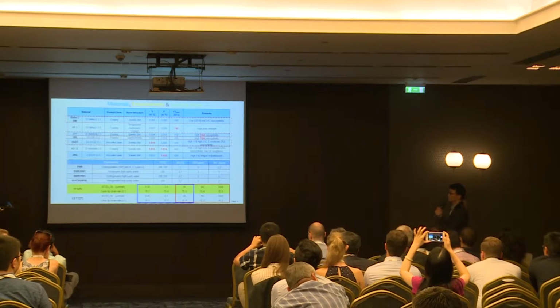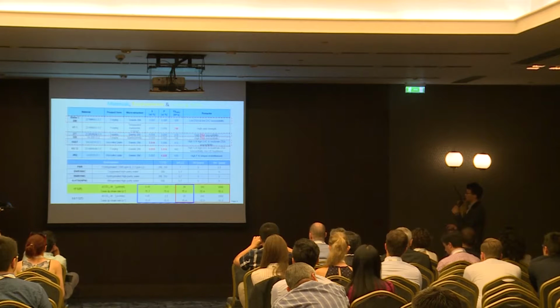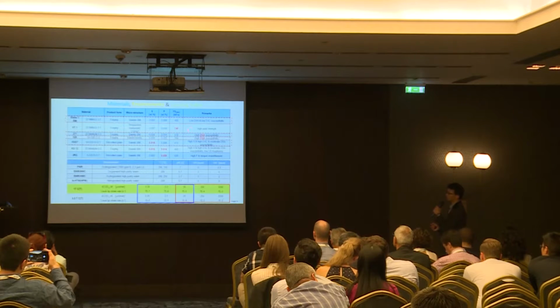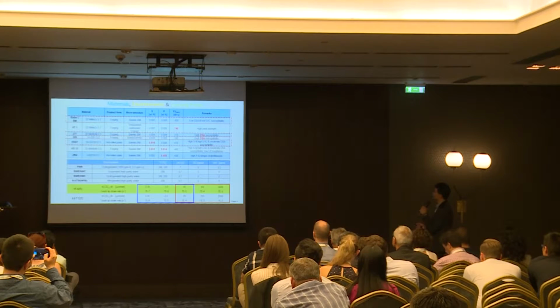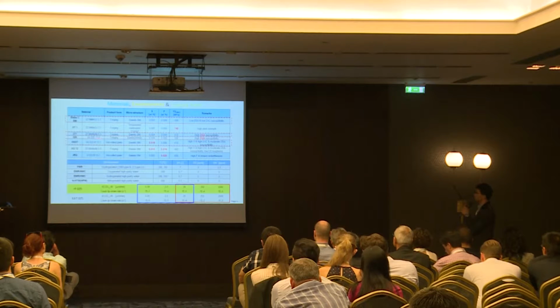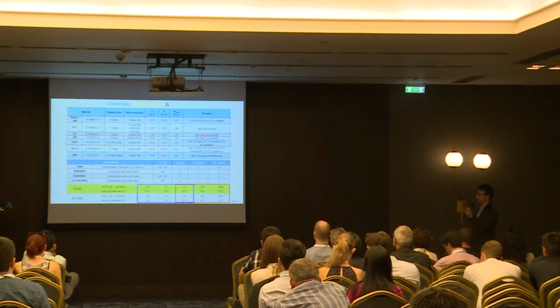Taking all this information in mind, about 3.5 years ago at Paul Scherrer Institute, we initiated these projects to systematically characterize the high temperature and hydrogen effects on the reactor pressure vessel. So we have investigated 7 kinds of RPV steels with different properties. And today I'm going to talk about 3 of them. The first one is the base metal, which is a reference material, which has a low sulfur content and also low temper embrittlement agent. And the second steel has a high temper embrittlement agent. The third steel has a high sulfur content and high environmentally assisted cracking susceptibility.